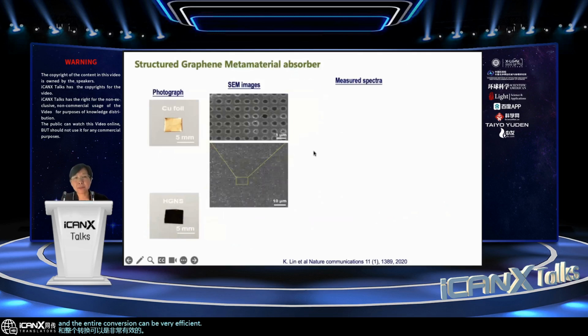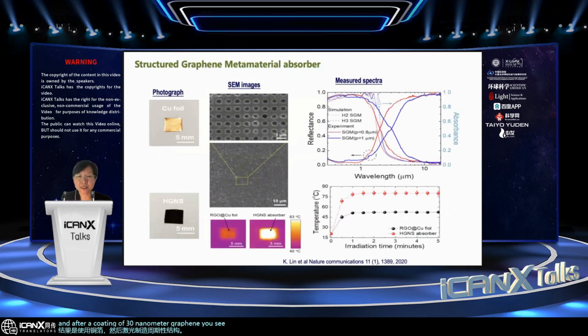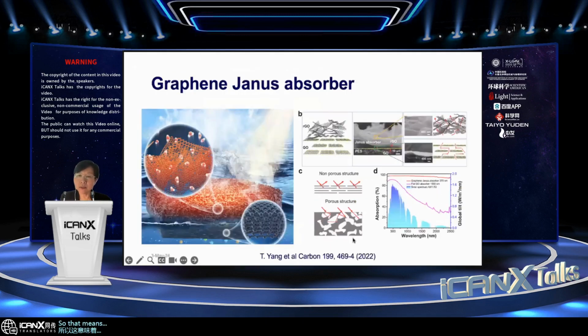So these are the experimental results. By using copper foil and then laser fabrication of the periodic structure, and after a coating of 30 nanometer graphene, you see that this absorption is really strong. The entire structure becomes dark, and then under sunlight, it can achieve 83 degrees immediately, in less than 1 minute. So that means we are able to convert the sunlight very efficiently into heat.